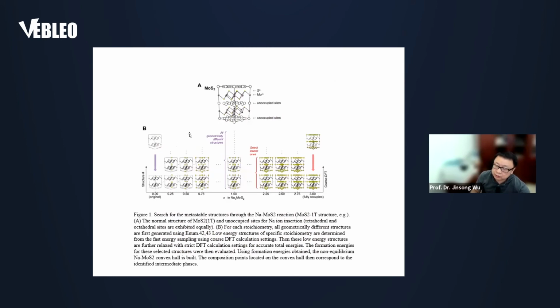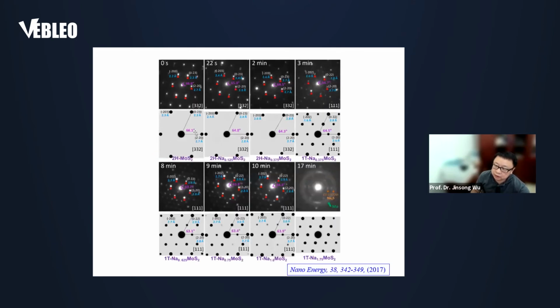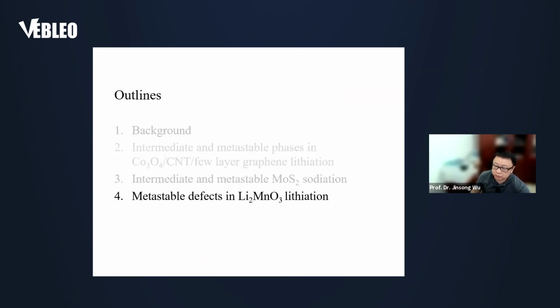Each intermediate structure is first defined by the DFT simulation by minimizing the energy. Based on that, we can then do the electron diffraction simulation and compare the simulation to the experimental ones by carefully measuring the d-spacings and the angles between them. All right, so that's my second story, and the last one I will show you is the metastable defects that we found in the lithium-rich electrode, which is Li2MnO3, or we can simply call it LMO.